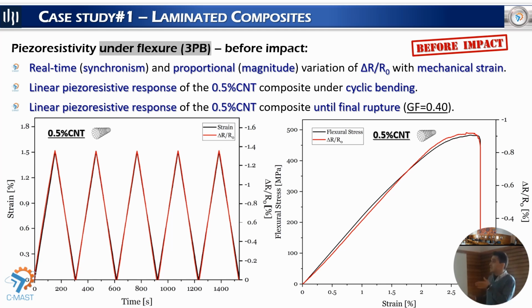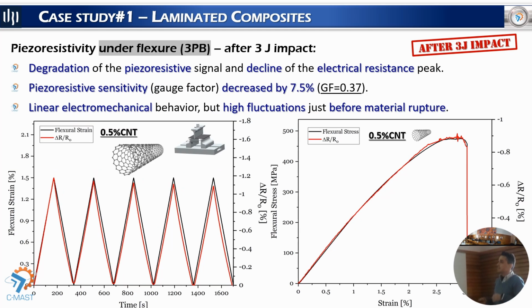These experiments are for samples before the impact tests. Then we study the same properties in the samples that were impacted, in this case 3 joule impacts, and here we see the same behavior but with some differences that indicate the permanent damage of the samples.